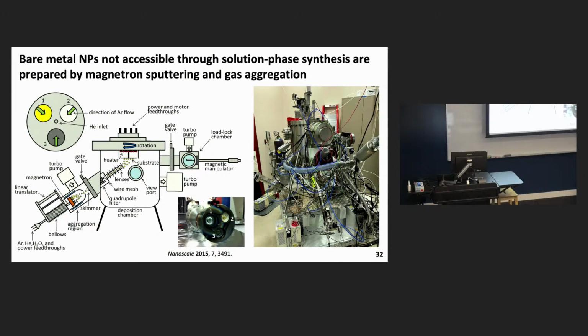which is using the device shown here. It's essentially a different type of soft landing device. Here, though, instead of using electrospray ionization, we're actually growing nanoparticles in vacuum using a process known as magnetron sputtering and gas aggregation. So you have metal targets located here, you flow in argon gas. This creates argon cations, which sputter the surface and create a metal vapor. That vapor is cooled through collisions with the wall. This causes nucleation and growth of clusters in a 2 to 15 nanometer size range.